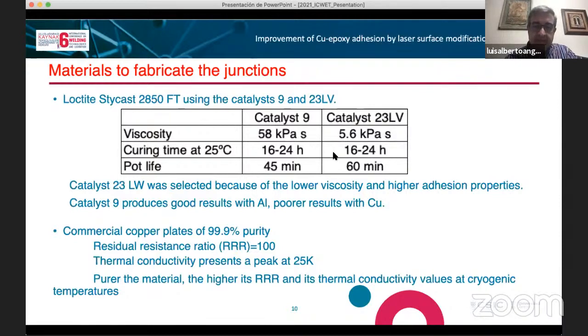The copper were commercial copper plates of 99.9 purity. The residual resistance ratio, the ratio between the resistance at room temperature and at 4.2 Kelvin, is 100. And this purity also means that we have high thermal conductivity. The thermal conductivity exhibits a peak around 25 Kelvin. The purer the material, the higher the residual resistance ratio value and the thermal conductivity at low temperature. You must think that we are working in an application that usually works at temperatures around 50 to 70 Kelvin.